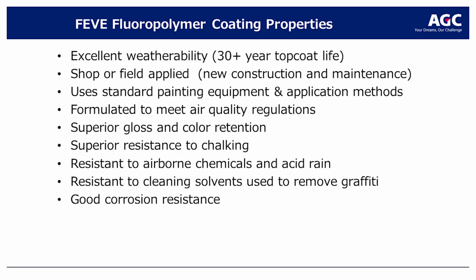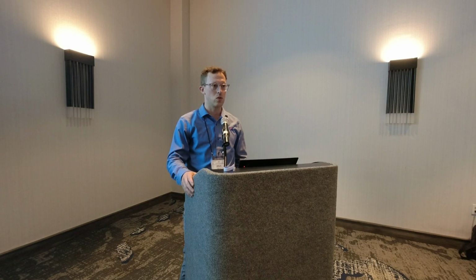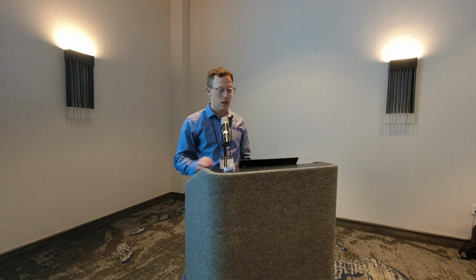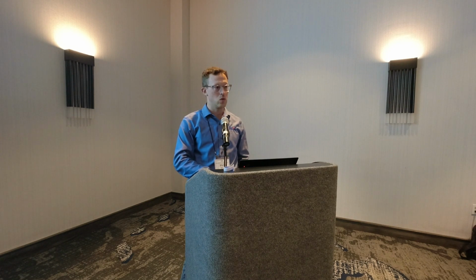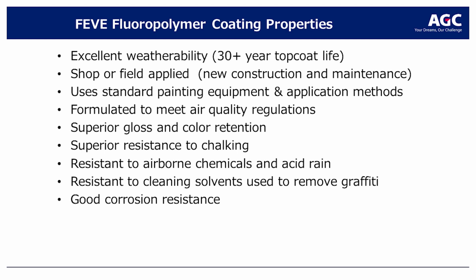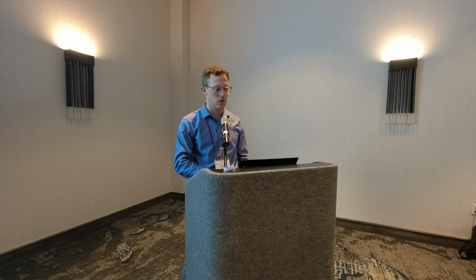It can be shop or field applied, new construction, or even on maintenance. So if you want to start fresh, but the reality is we're all looking at preservation, you can use this as a preservation coating as long as you do your surface prep correctly. And you're going to get that resistance to weatherability, that chalking resistance, that resistance to chemicals that you use for a lot of the salts that you're using. I know it's less important here, but for some of the coastal environments within the salty environments.